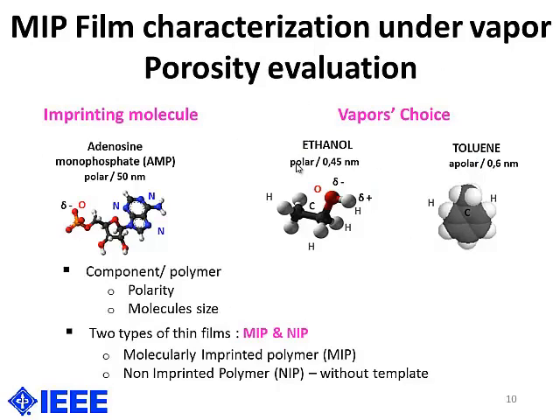We have chosen ethanol and toluene as complementary compounds to illustrate that, as polar and apolar molecules compared to the model target compound, which is a polar molecule. Two types of thin films have been deposited on the SAW devices. Some SAW devices were coated with a MIP film and some other ones with a non-imprinted polymer, with exactly the same solution but without the target compound, without the template.